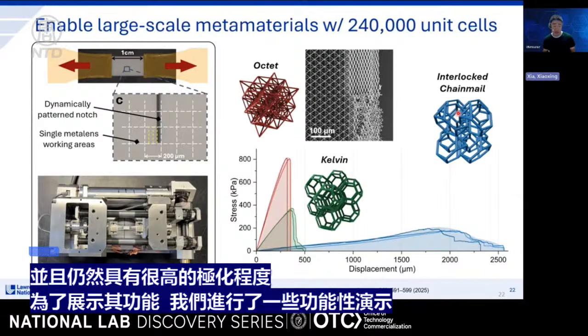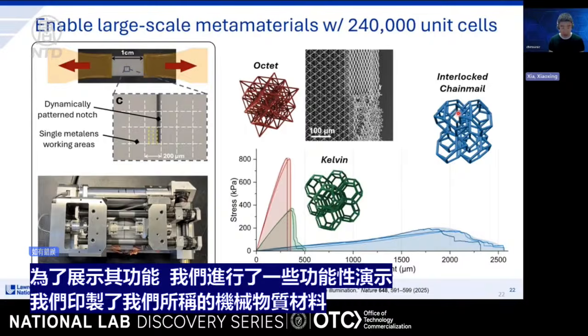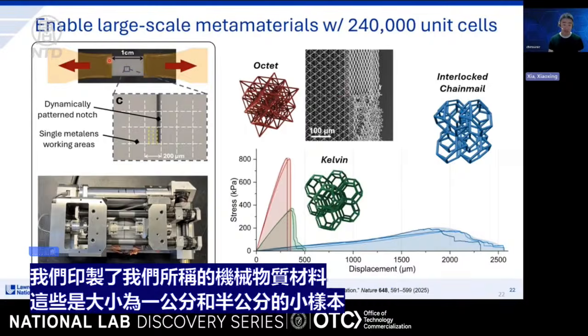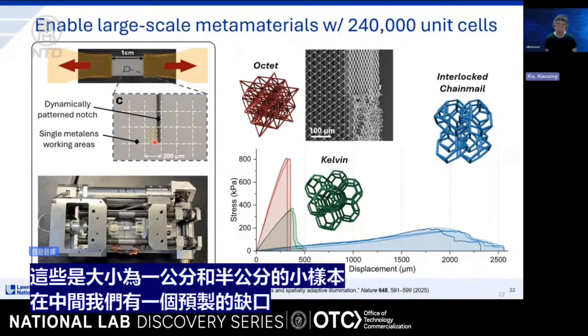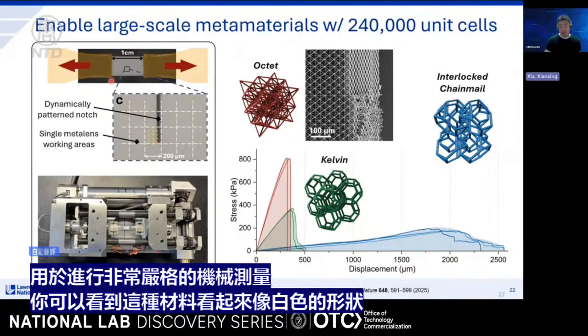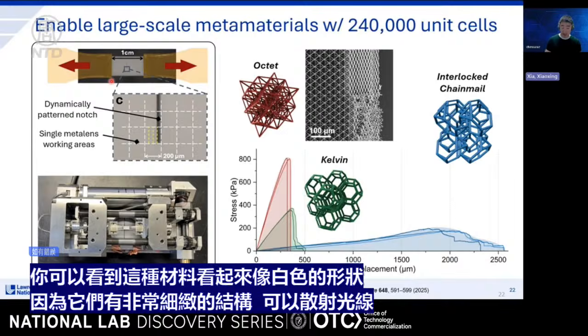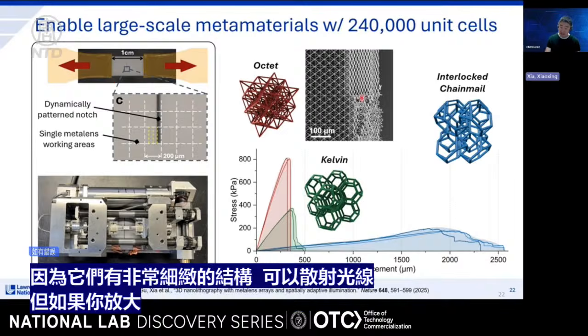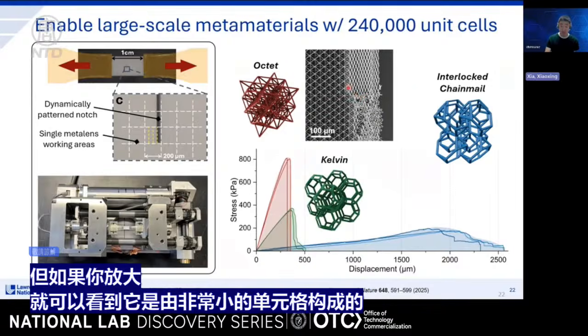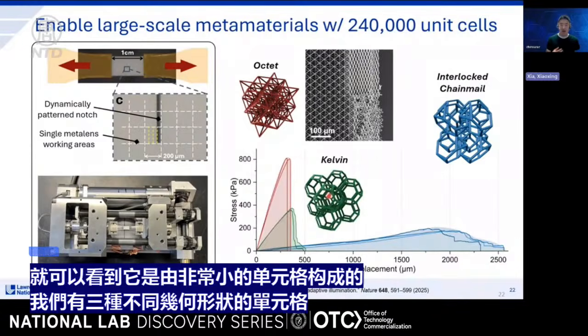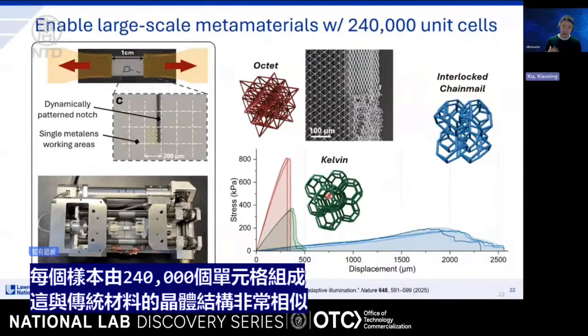So here we printed what we call mechanical metamaterial. Those are little coupons of material that are 1 centimeter and 0.5 centimeter in size. And in the middle, we have a prefabricated notch for a very rigorous mechanical measurement. You can see that the material looks like a white foam because it has a very fine structure that scatters light. But if you zoom in, you can see it's made out of very small unit cells. We have 3 types of different unit cell geometry, and each sample is made from 240,000 unit cells.